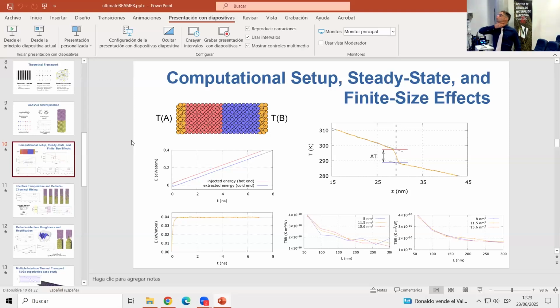And that is that you have, of course, a TBR which is dependent on the equilibrium conditions that you actually have, which in this case is determined by the thickness of the layers, which of course is a competition between the thickness and the phonon free path. This is obvious, no? Yeah, I think it also. I mean, to be honest, I haven't thought much about this when I was studying the system, but I would say yes.